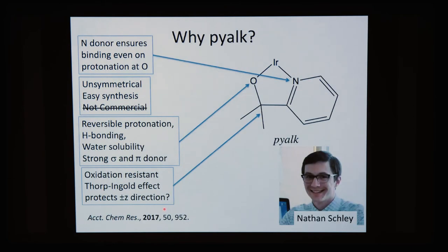So why pyalk? Well, it turns out that the nitrogen donor ensures binding even if the oxygen is protonated. And it's unsymmetrical, easy synthesis, and I like unsymmetrical ligands. Reversible protonation at the oxygen, hydrogen bonding at the oxygen, water solubility enhanced by that oxygen, and the oxygen is obviously a strong sigma and pi donor.